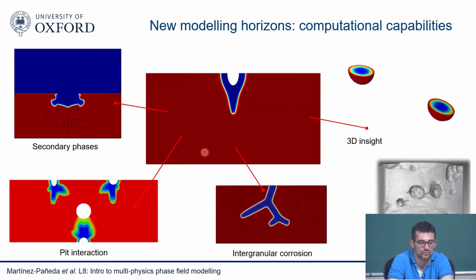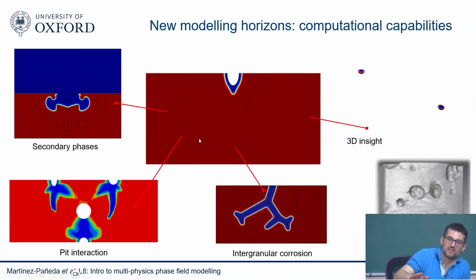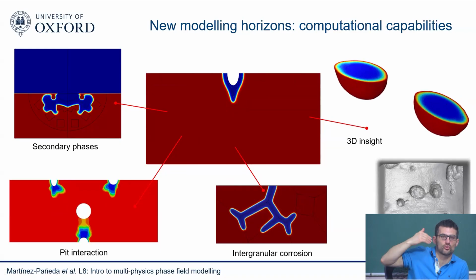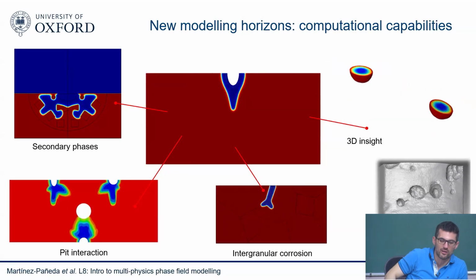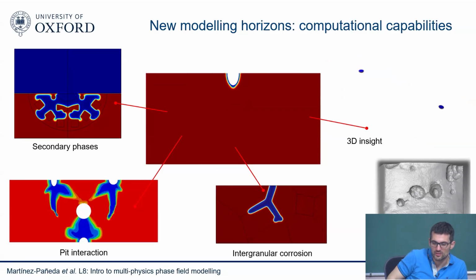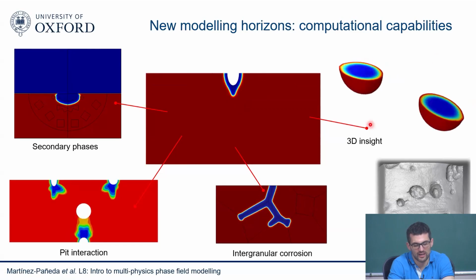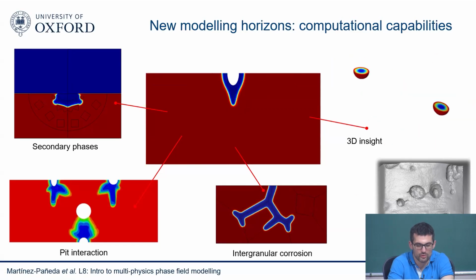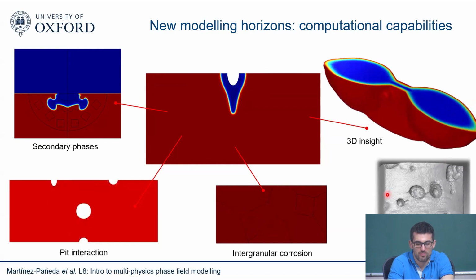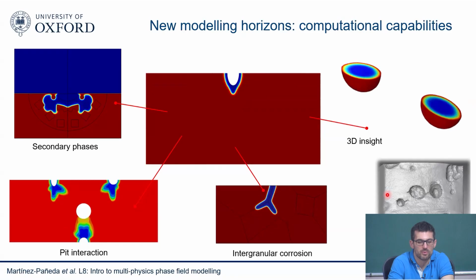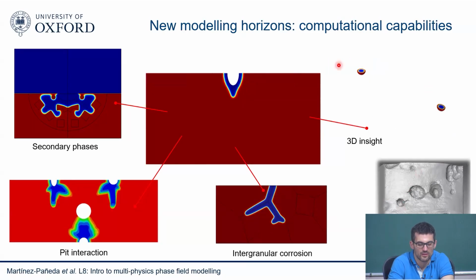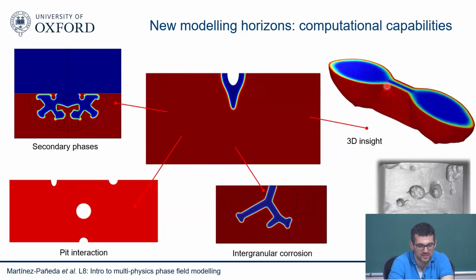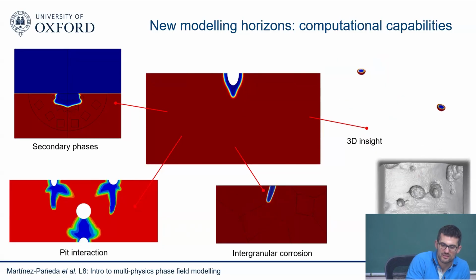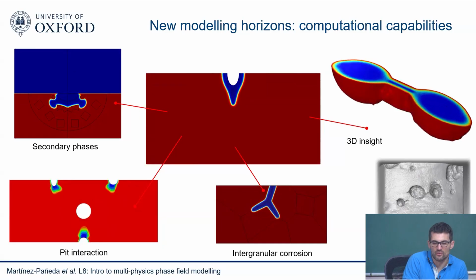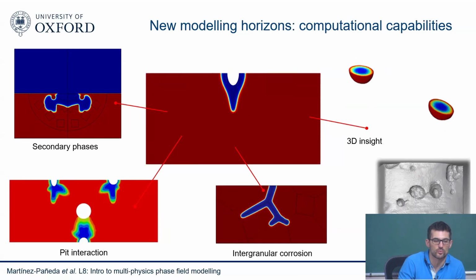You have various techniques to show how you can interpolate properties in space, and you can say my corrosion resistance, so to say, in my grain boundaries in this case is going to be weaker than in the bulk. So corrosion might be favored in the grain boundaries. And you can see also we can have 3D. So there's a lot of discussion going on now because of XCT synchrotron experiments where people are seeing interesting effects in terms of how the pits grow and how the pits interact with each other. And we can see that using our corrosion capabilities, we can capture precisely that pit interaction. So I think the models are powerful. The computational challenges have been addressed, and I think this is what gives us an opportunity to resolve all the complexity that comes with corrosion problems.